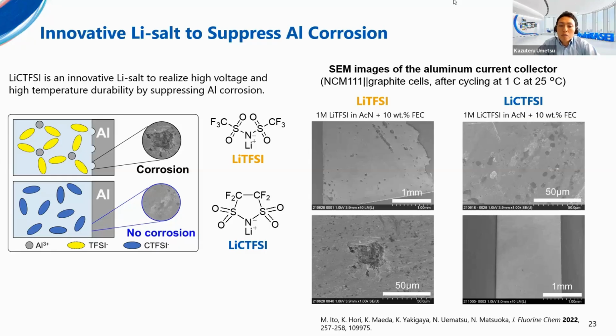However, lithium CTFSI, this cyclic imide salt, does not cause aluminum corrosion, even at a higher voltage, and can be used as a sole salt. So this means that there is no need to use LiPF6, which is unstable to heat, and it has the potential to achieve high temperature and high voltage that were previously not possible.